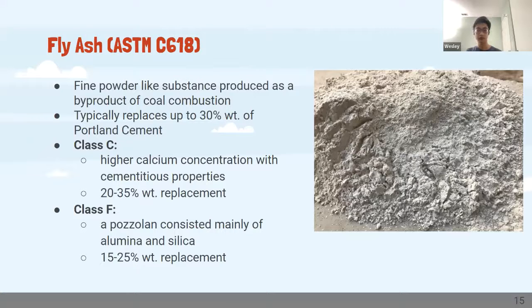And it's further divided into two different classes. So class C fly ash, which is higher in calcium concentration and has cementitious properties, can usually replace Portland cement by a range of 20 to 35 weight%. And for class F, it's more of a pozzolan that consists mainly of alumina and silica and can replace Portland cement by a range of 15 to 25 weight%. And the picture on the right is a picture of fly ash.